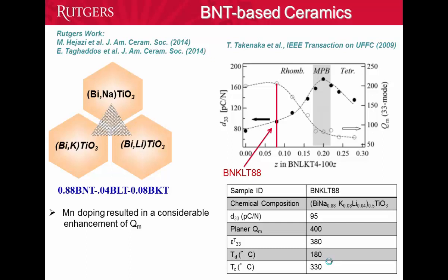We have chosen the rhombohedral side because it has the highest mechanical quality factor of 400, a piezoelectric coefficient of 95, permittivity of 380, and depolarization temperature of 180. And you can see the chemical formula here.